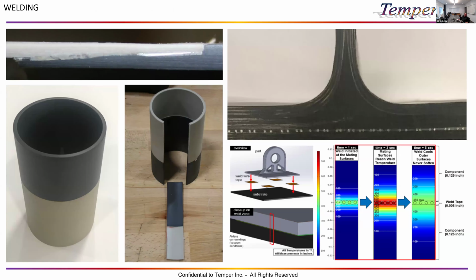We also taken the technology and we've adapted it to welding. So in this case, we've got smart susceptor wires. These wires can be coated so that corrosion becomes a non-issue. These wires are embedded inside of PEEK resin, and these are 2 PEEK parts that were welded together.